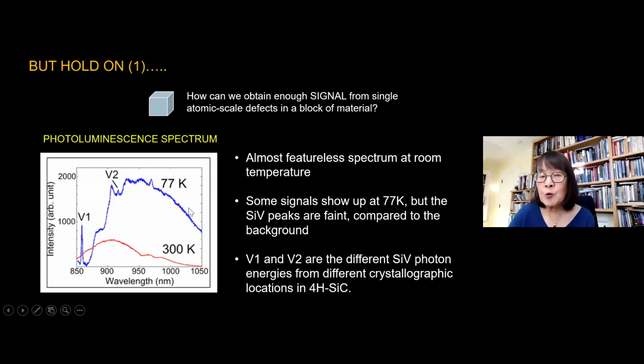If I cool my sample to 77 Kelvin, liquid nitrogen temperatures, I begin to see some characteristics, some identifying indication that there is indeed a silicon vacancy within. But what you can see is that the peaks are faint and they're almost lost within the background. And notice here that I have two peaks identified. One is called V1, one is called V2. These are in fact the different signatures from the slightly different silicon vacancies.